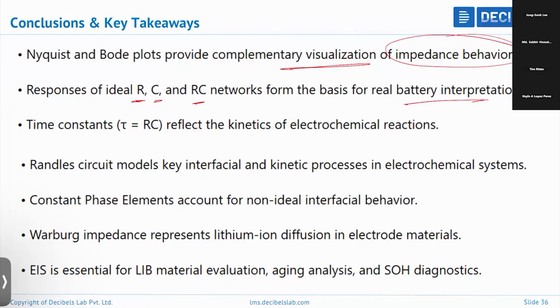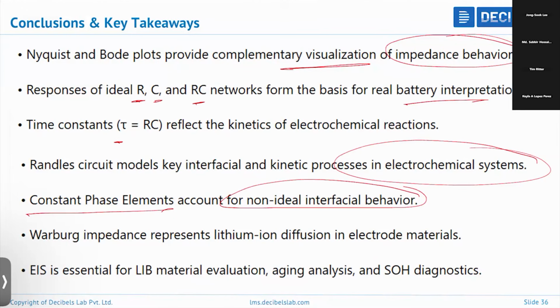So we have also understood that the time constant RC reflects the kinetics of electrochemical reactions, and equivalent circuit models reveal key interfacial and kinetic processes in electrochemical systems. And also we have discussed that constant phase elements account for non-ideal behavior of the battery, and Warburg impedance represents the lithium-ion diffusion in electrodes, the nature of the diffusion. And so overall, EIS is essential for LIB material evaluation, aging analysis, and also SOH diagnostics. So with this, I conclude my discussion.